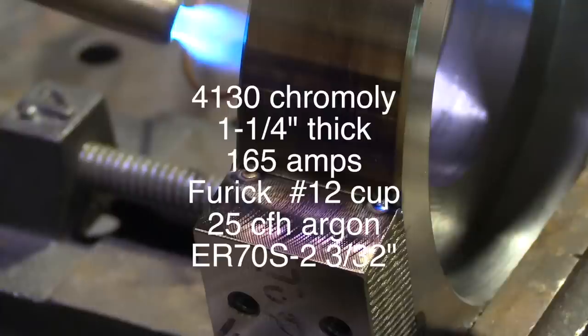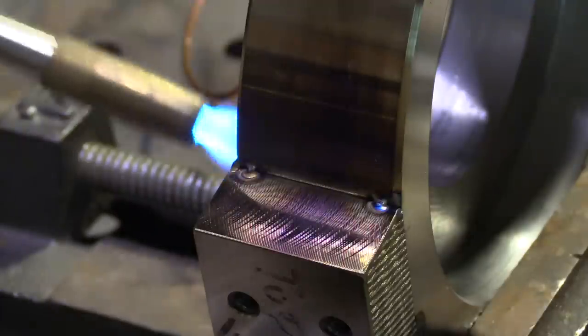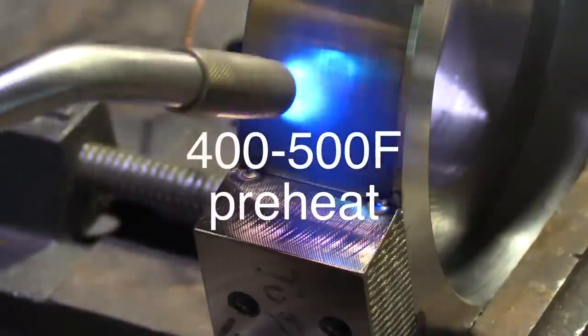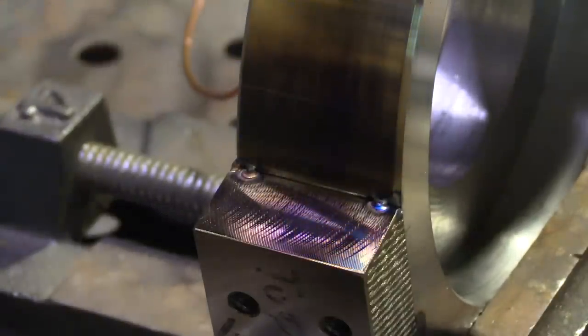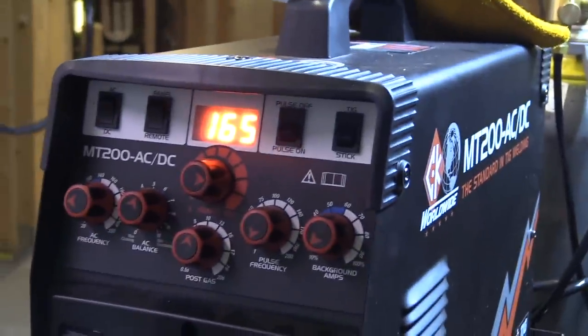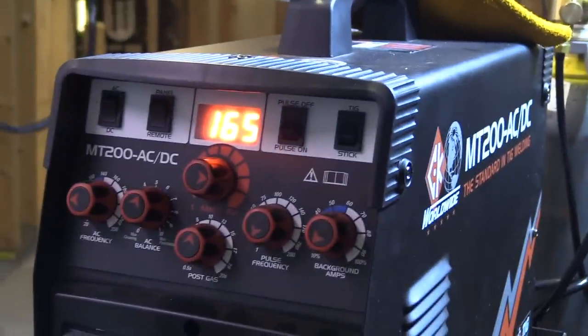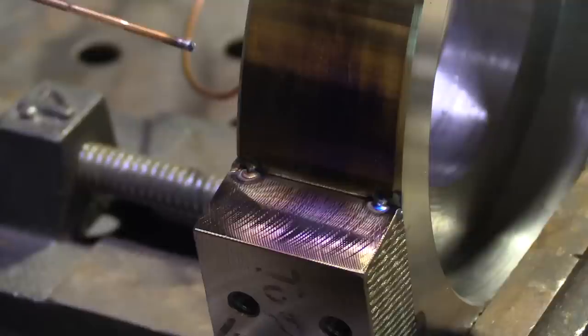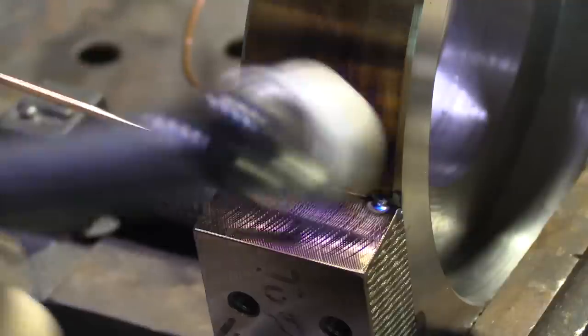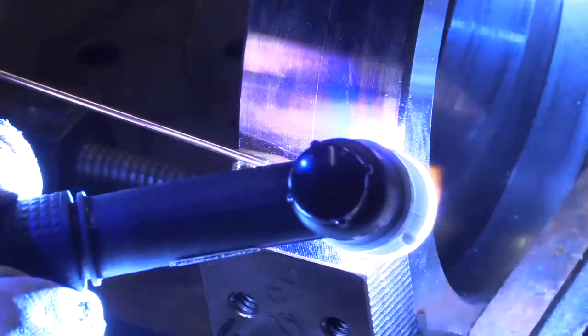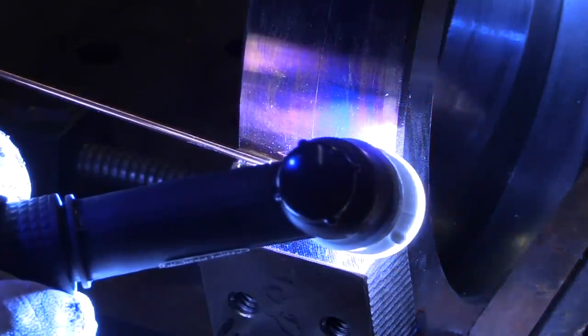I used to do quite a bit of work for small machine shops, and this is one of the jobs that I did a while back. A big, thick chunk of 4130 chromoly. Have no idea what this was going to be, but I knew it needed a preheat. So I preheated to around 500 degrees, set the machine on 165 amps, decided to use what's called a lay wire technique here, which means I just welded it plenty hot, but I walked right over the rod without dipping in and out of the puddle. And that's just one technique that works.